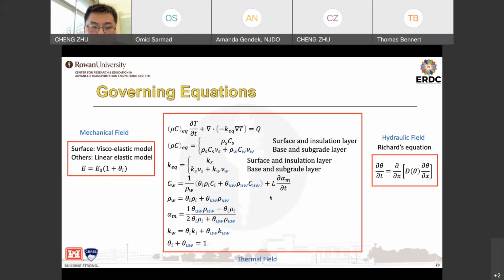Here are some of the governing equations we used for the multiphysics field, including the mechanical field, thermal field, and also the hydraulic field. For the mechanical field, the material is assumed to be viscoelastic for the HMA layer, and the other materials we simplify to be linear elastic. For the thermal field, we consider mainly the heat transfer process. Because it has ice in it, the subscript i indicates ice, and uw means unfrozen water. So we consider 2 phases in the soil, including both ice and water. And the hydraulic field is governed by the Richards equation.